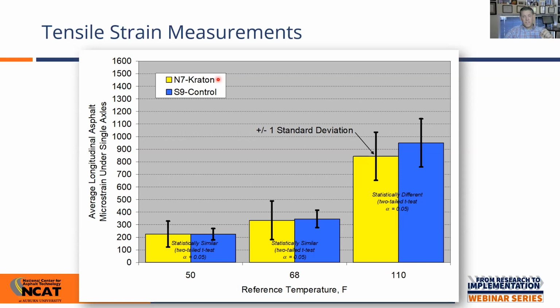And so we should see it, if everything else was equal, we would see a much higher strain in that section, but the changed properties due to the high polymer loading means that we see very similar, statistically similar strain levels there. And then when we get to the warmest temperature, let's say 110 degrees Fahrenheit, the increased modulus that we determined through back calculation and testing gave us a lower strain level.